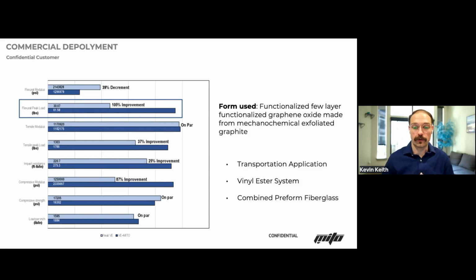Another use case is that we deployed a functionalized few layer functionalized graphene oxide made from a mechanochemical exfoliated graphite. A lot of words, but essentially this graphene oxide was made from a chemical and grinder process to be able to blow it apart. We functionalized on top of it and it was put into a transportation application. We chose this material because it's a vinyl ester system within our transportation, so we had to meet cost. And so when we put our chemistries into it, it reactively dispersed into the resin. And these results here are at a 0.1% by weight concentration within the vinyl ester, put into a preformed fiberglass mat. It was an e-glass mat, tested to ASTM standards.